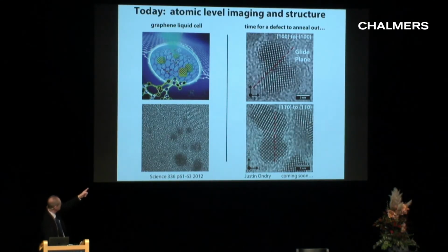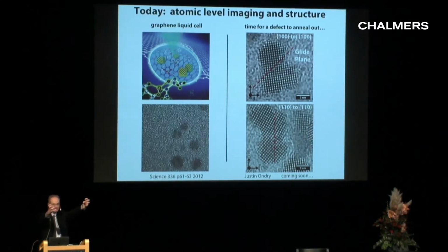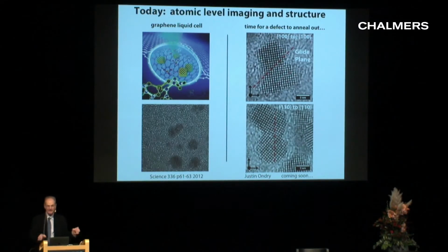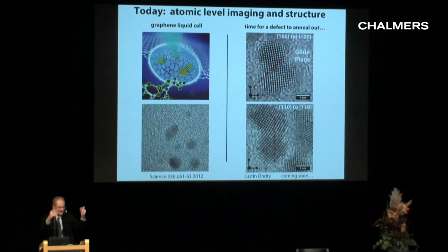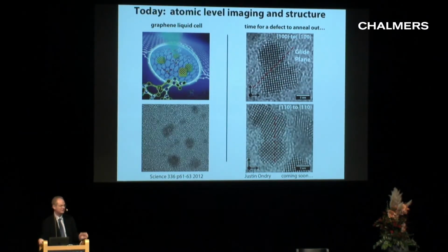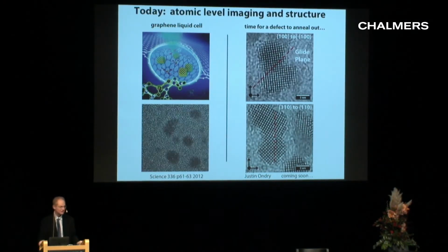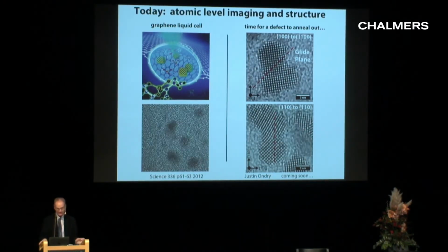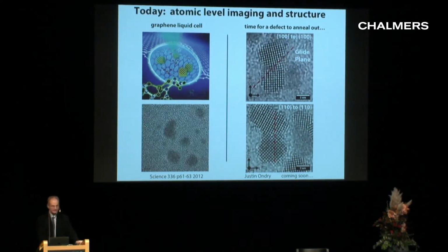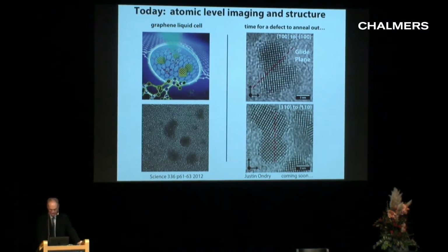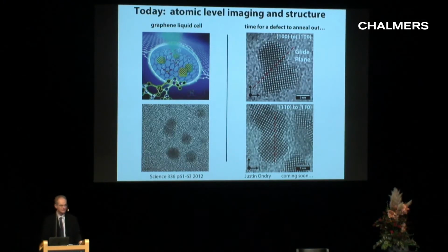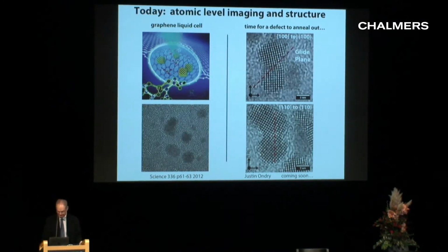On the right there, you see some very current experiments where we take two crystals and we join them together, and we can actually see how long it takes for a defect to anneal out. We can do that as a function of the size. We can connect them with different orientations, and we can measure how long it takes. And indeed, there are scaling laws for that look very much like the ones that you would expect. In other words, it scales exponentially with volume and things like that.